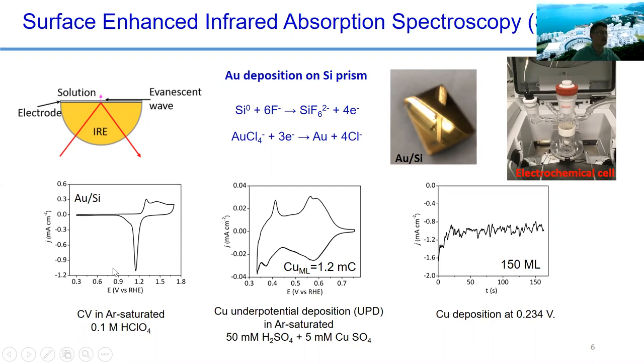So after that, we deposit a copper layer. Yeah, so the copper layer we can deposit using the electrochemical method, right? So first we need to determine how many charges are needed to deposit one layer of copper, okay? So we're using copper underpotential deposition to figure out the charge needed to make one monolayer of copper. Okay? So in this case, it's about 1.2 millicoulombs to cover the whole surface, right? Then we use the electrochemical method, keeping the potential at 0.234 volts, to deposit the copper.